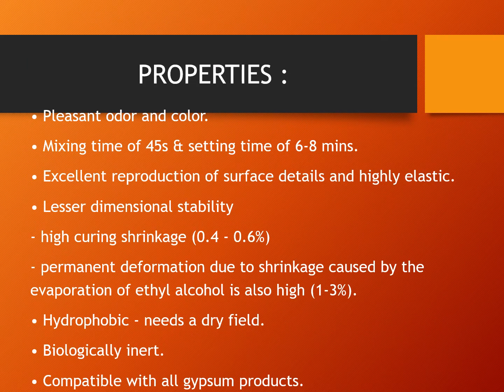Now let's see the properties. It has a pleasant odor and color, mixing time of 45 seconds, setting time 6 to 8 minutes, excellent reproduction of surface details, highly elastic, lesser dimensional stability and high curing shrinkage. It has permanent deformation due to shrinkage caused by evaporation of ethyl alcohol. It's hydrophobic, so needs a dry field, biologically inert, and it's compatible with all gypsum products.